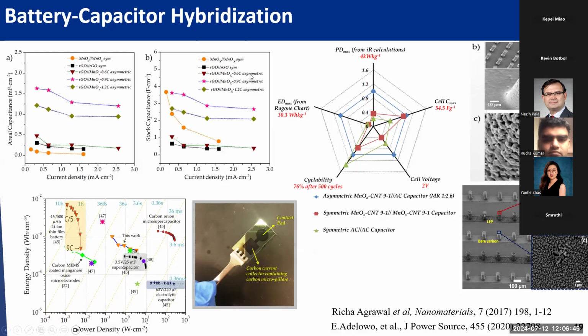But if we want to make a high energy capacitor without reducing the power density, my group was trying to make the battery capacitor hybridization. We make the C-MEMS array, for example. This is Ebenezer's work. Now he's at Intel Corporation. His work is miniaturizing the carbon MEMS-based lithium-ion capacitor. So you can see he has a bare carbon electrode and another paired electrode for the battery electrode, which is lithium iron phosphate. That's a very good battery cathode material.